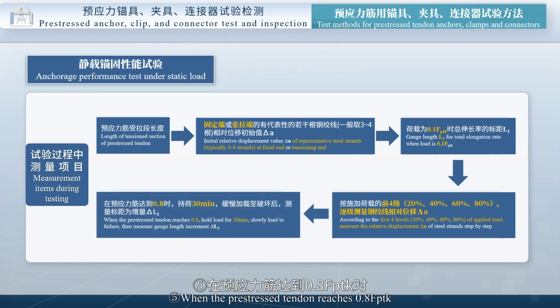Fifth, when the pre-stressed tendon reaches 0.8 fptk, hold the load for 30 minutes. Slowly load until failure occurs. Measure the gauge length increment delta L1.